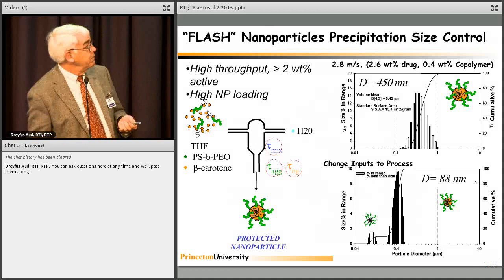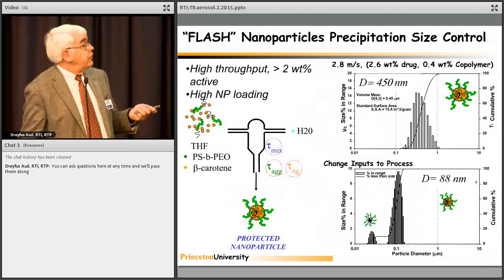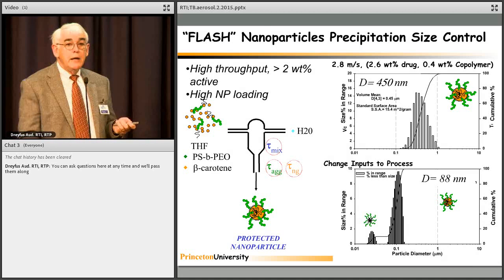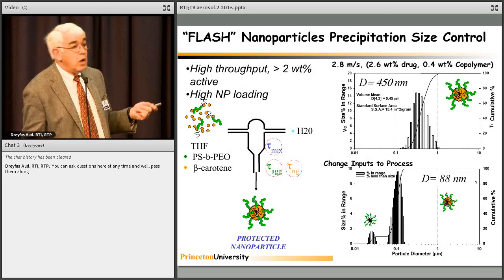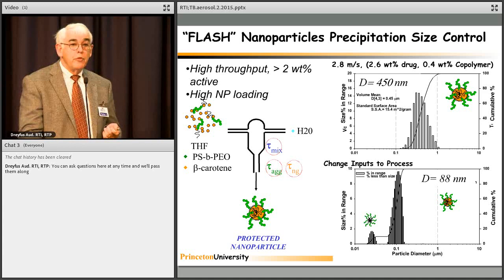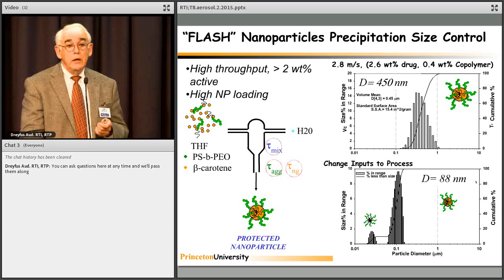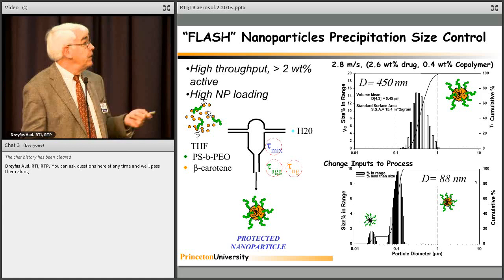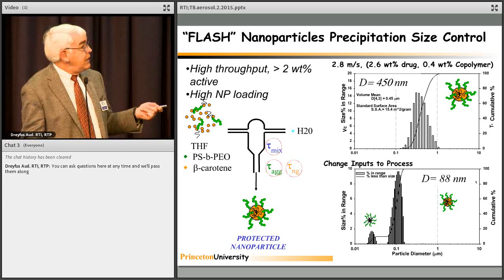So this is the range of particle size that we can conveniently cover. The top one is 450 nanometers mean size. Everything is within one decade of size, which is narrow in this sort of field. And we see we have six times more drug or contents than block copolymer. So the loading that we are able to get with this is much higher than the loading that most people get in the nanoparticle field, where 2 to 3 to 4% is normal for most loadings of hydrophobic materials in PLGA particles, for example. If we change the supersaturation, here we end up with 88 nanometer particles.